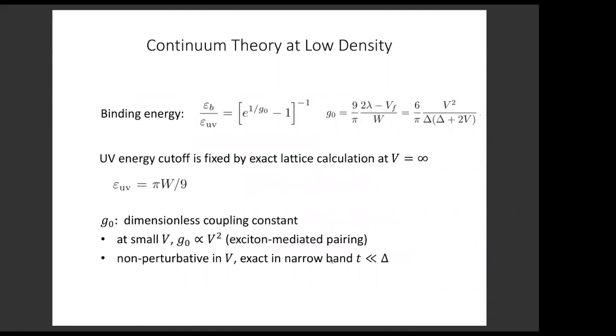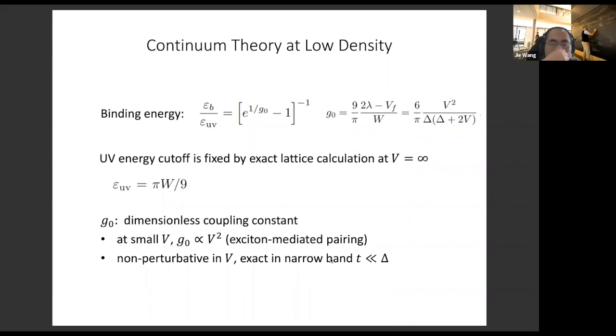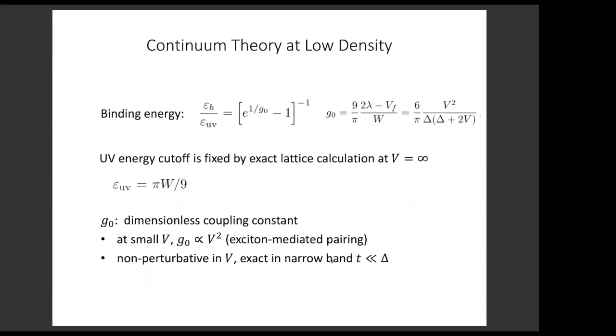Also, to show that this derivation is really a good approximation, we compared the binding energy from this continuum theory, the BCS problem, with our lattice calculations. Here the binding energy depends on the UV cutoff and on the coupling constant G0. As I said, we already have the full expression for G0. The UV cutoff is fixed by the exact lattice calculation when the interaction V is sent to infinity, in which case we know the binding energy exactly. So this fixes the UV cutoff, and then we can compare the results. Next slide.